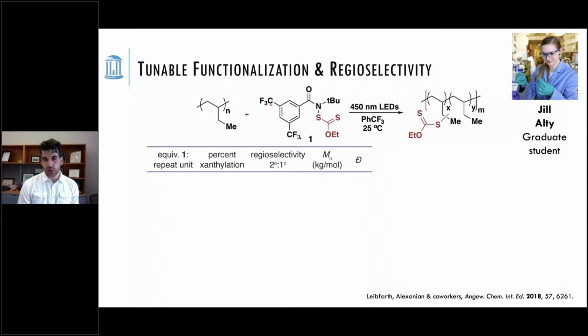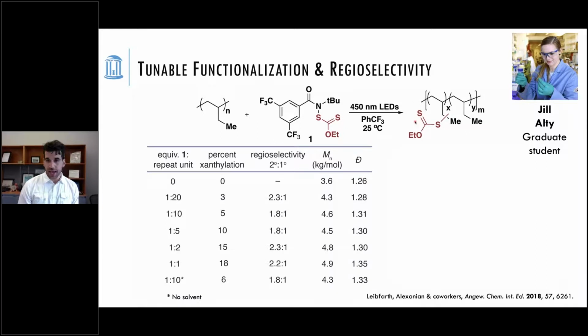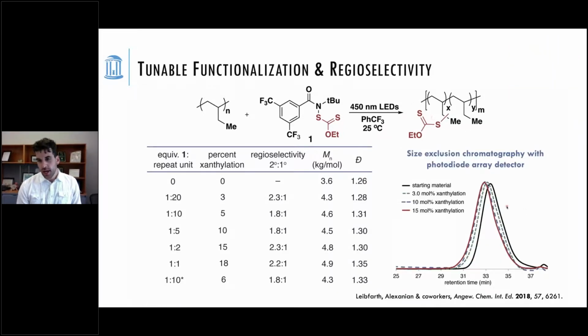So she took this reagent, which is actually just a solid powder, right? You take a ground up polymer, sprinkle in a bit of this solid powder, and you're able to add this chemical functional group onto this polyolefin. The really cool thing is you can add a variety of densities of this functional group. We use a characterization technique called size exclusion chromatography. If you were breaking those polymer chains like in the previous technology, you would see a really large peak come up right here at about 37 minutes retention time. But when you add a variety of amounts of this chemical functional group to the polymer, you don't see this peak arise at 37 minutes of retention time in any of these instances.